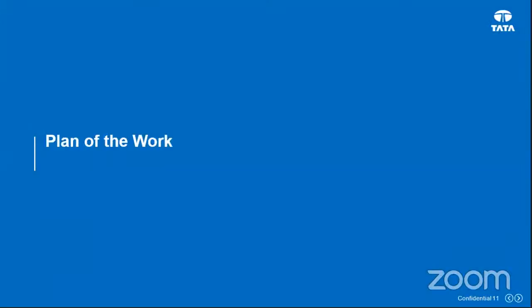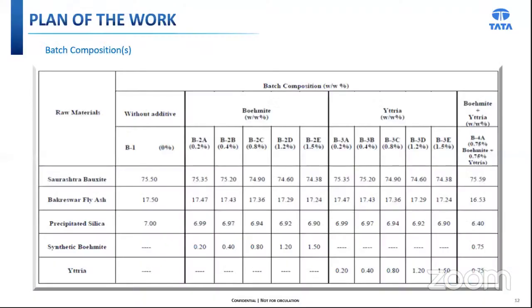Now, coming to the procedure, the plan of the work. These are the batches that have been selected. Batch 1 is without additive. Batches 2A to 2E have boehmite percentage varying from 0.2 to 1.5%. Yttria batches are 3A to 3E, and the last batch is batch 4A. It consists of 0.75% yttria and 0.75% boehmite.